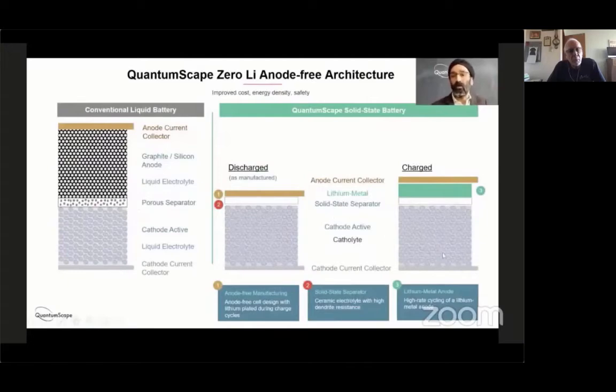When you first charge it up, lithium ions flow out of the cathode through the separator and deposit themselves on the separator, creating a layer of pure metallic lithium, which is the anode. When you discharge the cell, it goes back to its initial state, and you can see that it cycles back and forth between these 2 states.